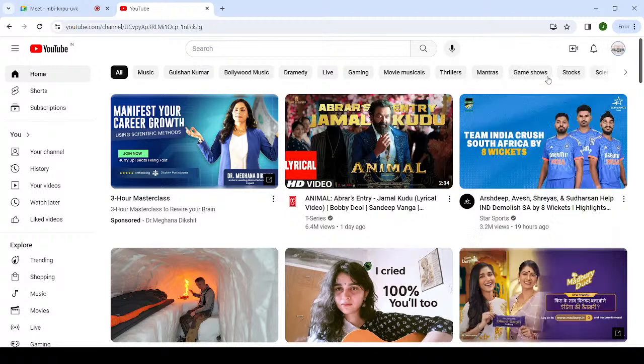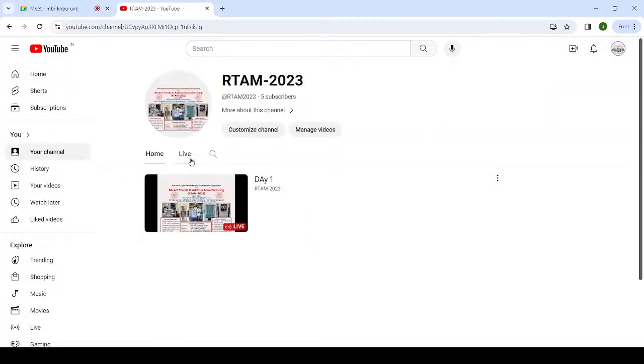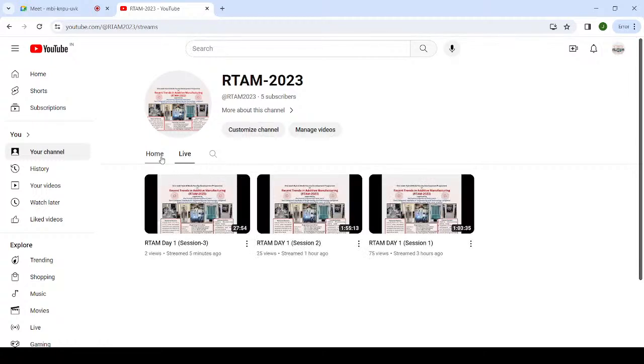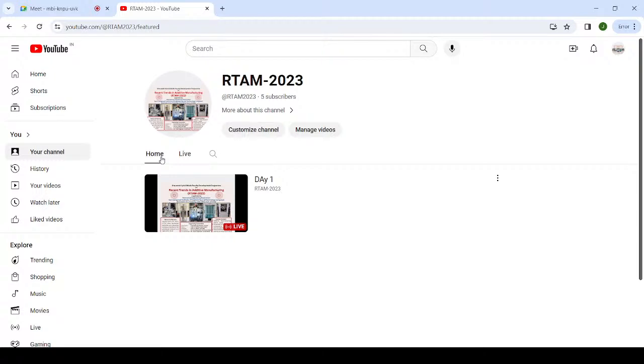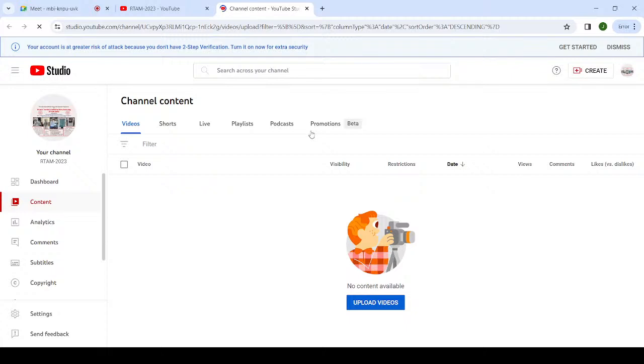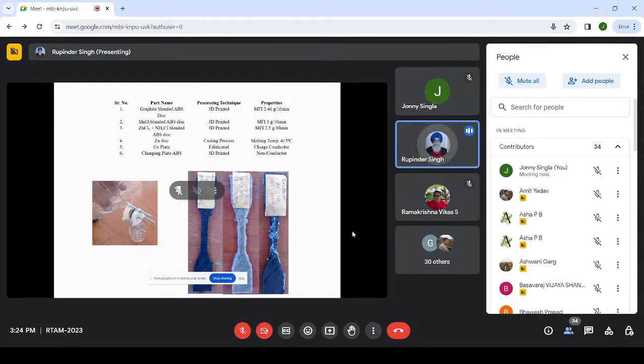Once we assembled this system, we did not get the voltage immediately. We were really disheartened, wondering why this was not happening, because the theory says that if these salts are put together, they are supposed to convert the chemical energy into electrical output. One probable reason was that since I am putting the ABS in as a binder, being an insulator it may have blocked the flow of charge from one disk to another. So we took some acetone and put some acetone drops on the interface, and suddenly we immediately got 1.5 volt.